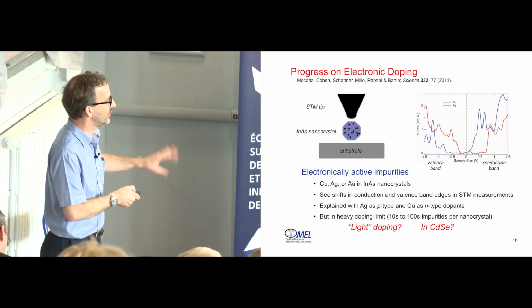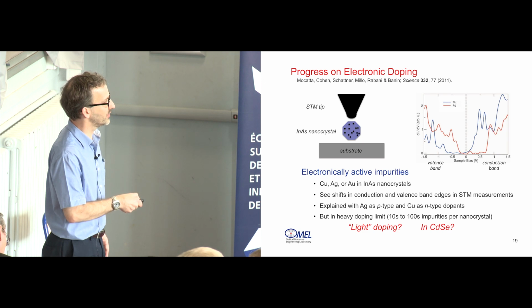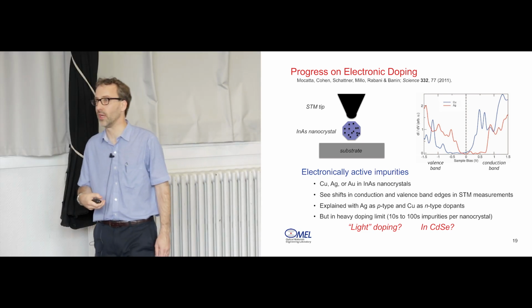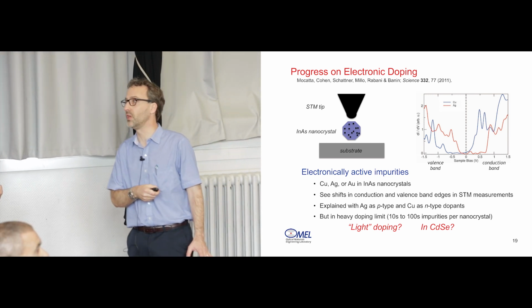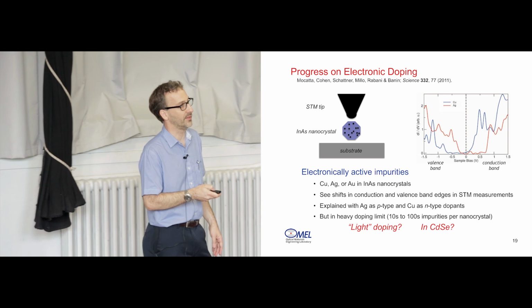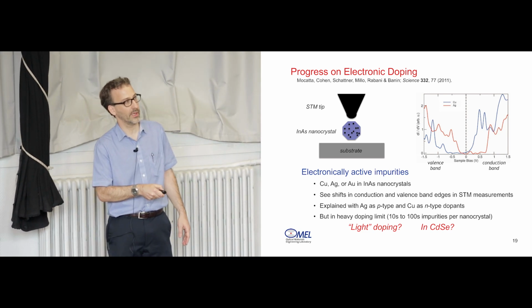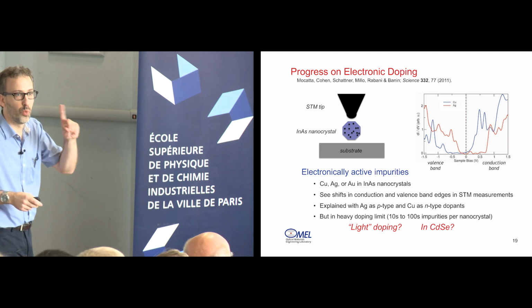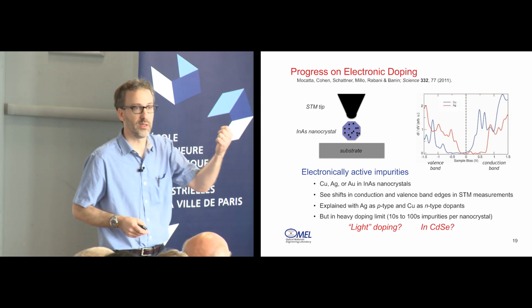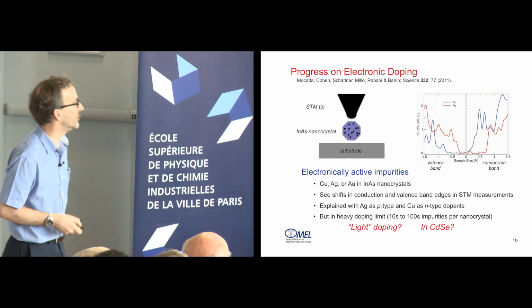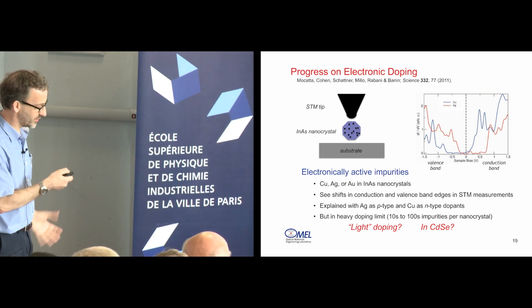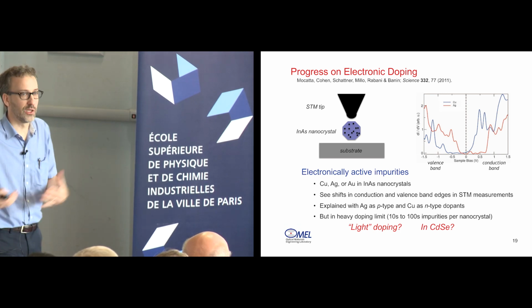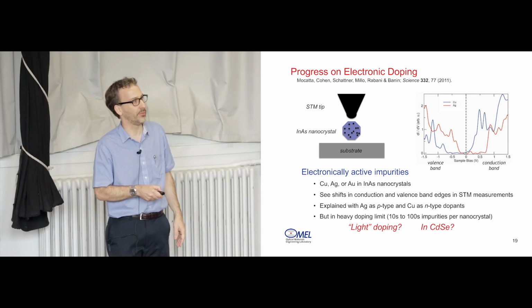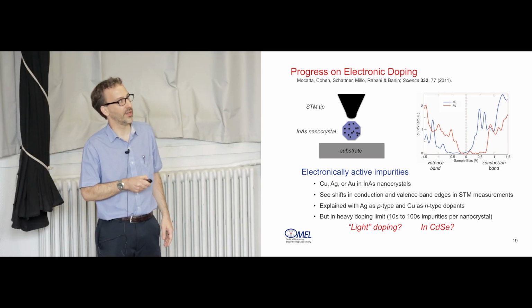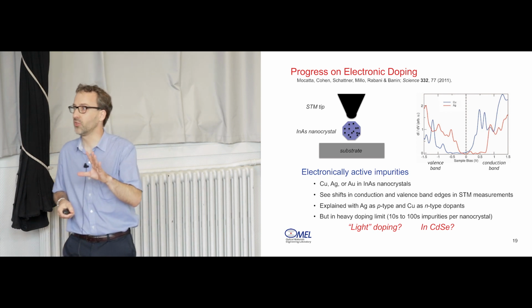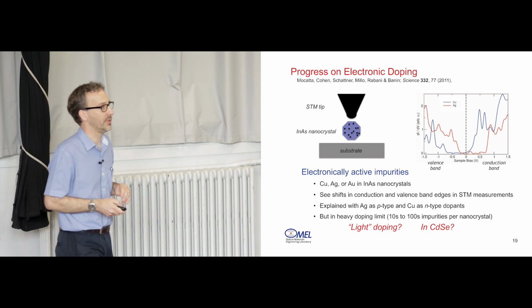Now, one thing that we wanted to do to complement these results is that these were in the heavy doping limit. They had tens to hundreds of impurities per nanocrystal. So my cartoon here with 14 impurities is on the low end of the limits that they were looking at. We wanted to look at light doping. And I'm putting light in quotes because even one impurity per nanocrystal is already in the high doping limit in the bulk, just because of the volume that each impurity will occupy will still be quite high in a bulk sense. But we can't go any lower than 1, right? So we're going to have to call it light doping. And then we also wanted to look at cadmium selenide instead of indium arsenide because, of course, we know so much about cadmium selenide that if anything changes, we should be able to detect it.